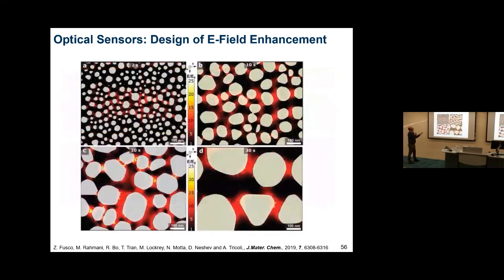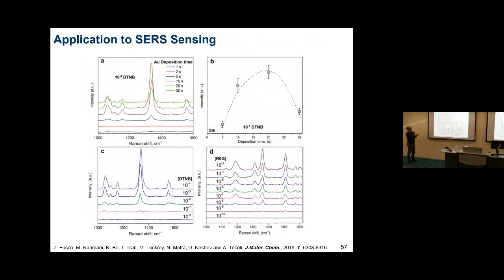When you do that, you can also model with COMSOL and others the electrical field between these structures, and see at which time you expect a stronger enhancement, then compare this result with SERS, for example, as a function of time.